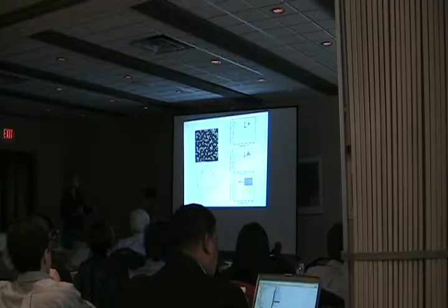But if we look carefully at what's going on plasmonically, if we start from the optical spectrum, this is all theory. This is quite a different time domain. We start from a single nanoshell, with a dipole resonance, and then a little higher order quadrupole resonance. So let's look at what happens as hybridization begins to happen with the nearest neighbor structures. If I go from a single nanoshell to a trimer, then the dipole plasmons begin to interact, and I get a broader, significantly redshifted dipole derived plasmon, and my quadrupole plasmon stays at the same wavelength as before. It shifts just a few nanometers, barely shifts. If I extend this to an entire array, then the dipole plasmon mixes and disperses really dramatically down into a band, leaving the quadrupole plasmon back at its original wavelength.